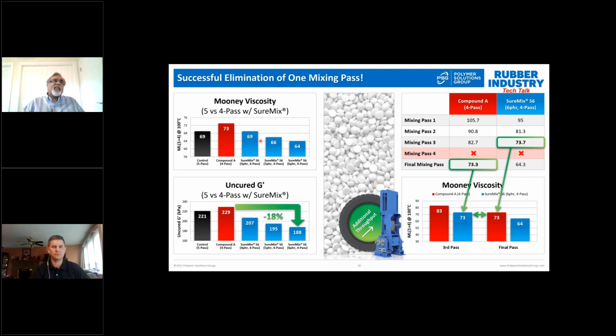We prefer to look at G prime, and G prime is more sensitive. And over here, it's important to note that while we saw 69 Mooney for the 5-pass control and 4 PHR SureMix, we see a lower G prime, 221 versus 207. But if you look at the 6 PHR, we've gone from 229, a reduction of 18%, to 188 kilopascals. So a significant reduction in G prime.